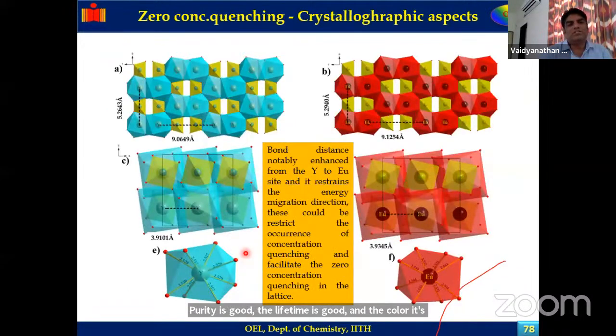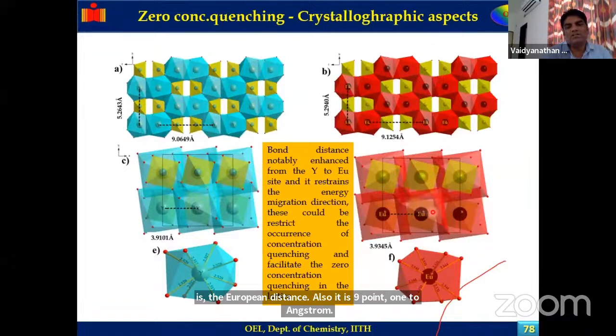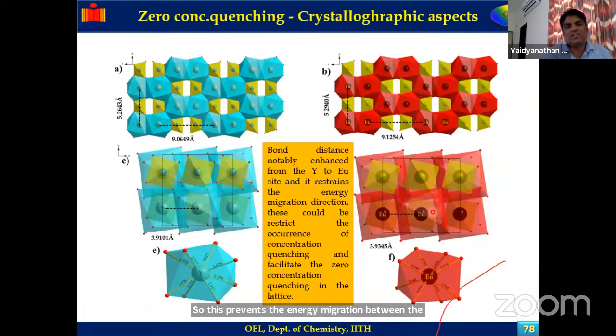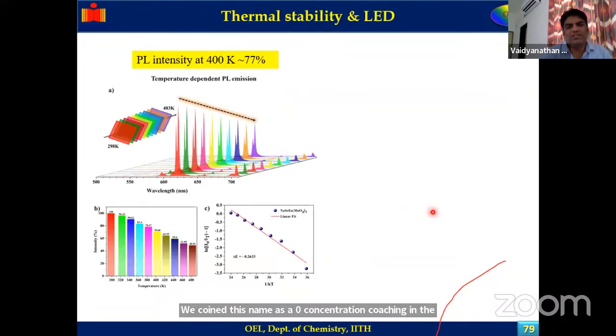This is because when you see the yttrium-yttrium distance, it's around 3.9 in this axis, whereas across the layer it is 9.06, and the europium distance is also 9.12 angstrom. So this prevents energy migration between europium and europium, and hence we get no concentration quenching. We coined this name, zero concentration quenching, in the paper. And 77% of the emission intensity is retained when you increase the temperature from room temperature to 400K.